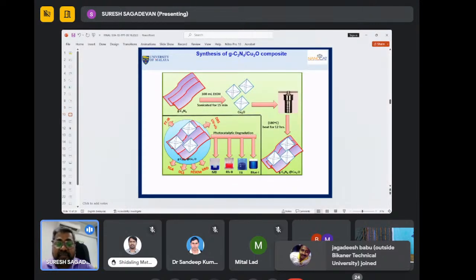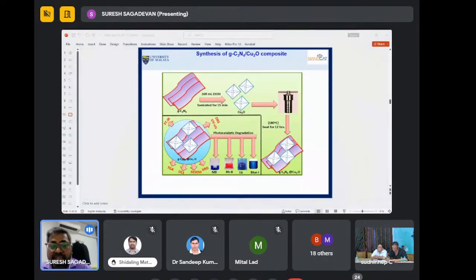This is the synthesis of the graphitic carbon nitride/Cu2O composite. It is a very simple hydrothermal method. As all of you know, this is a graphitic carbon nitride sheet, and then we took 100 ml of ethanol and sonicated for 15 minutes. This is the cuprous oxide, which has a octahedral shape, and combined together, the solution was kept at 180 degrees Celsius in a hot air oven. After heating at 180 degrees for 12 hours, you look at here, we got this graphitic carbon nitride with cuprous oxide composite.